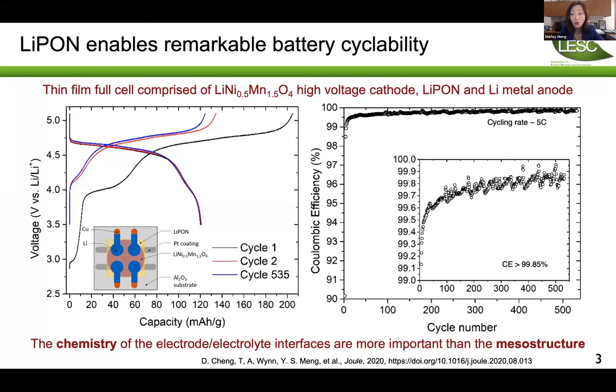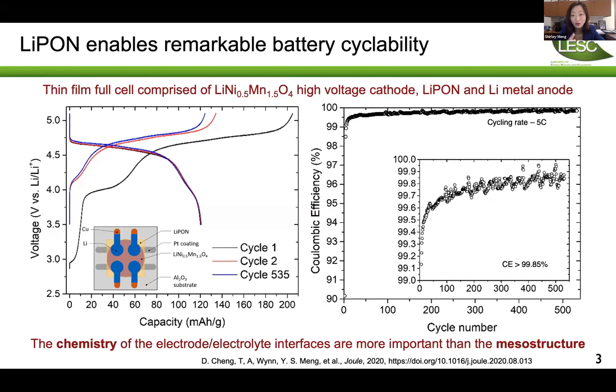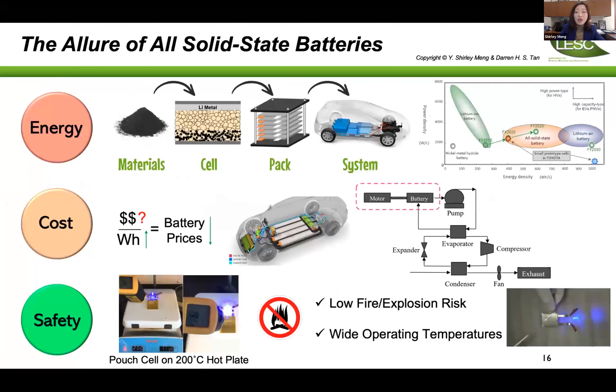This kind of interface has very unique properties — we know we have no problem obtaining 99.9% efficiency, and in the literature, 10,000 cycles have been demonstrated for lithium-LiPON batteries. We still have a long way to truly understand what constitutes a stable interface for the lithium metal anode. The thin-film lithium-LiPON interface is a good model system, but in thin films we only move 5 microns of lithium at a time, whereas in the pouch cell we showed, we're moving 20 microns of lithium per charge-discharge cycle — a really big difference.